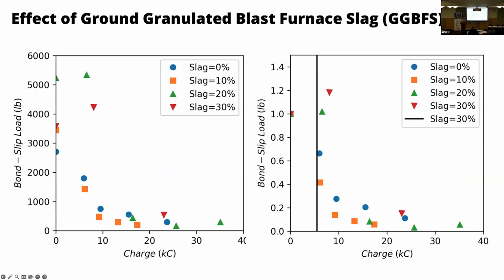However, slag itself gives some filler effect. Bond strength is a little bit better than normal concrete. That is a little bit of a controversial issue, so we are trying to interpret this one a little bit further. But anyways, once corrosion progresses, the amount of slag is just meaningless. So next.